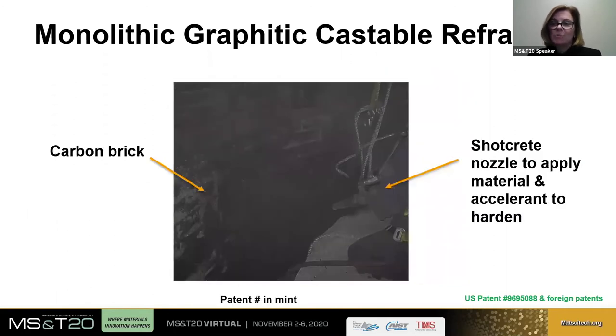We make and use this material to line the Bosch area of blast furnaces in several countries now. This has been installed both by manual shotcreting and robotically. While the monolithic graphitic castable is not identical to carbon brick, it offers a way to repair a carbon brick lining quickly in high volume and with reasonable properties.